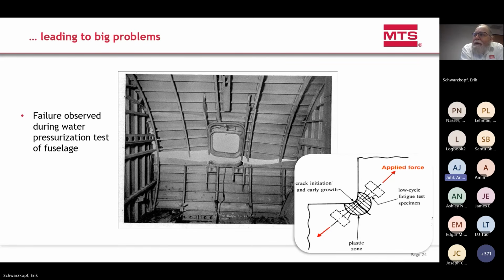The British engineers who made the de Havilland Comet needed to figure out what was going on. They took one of the airplanes, put it on the tarmac, filled it up with water, and pressurized and depressurized the fuselage, and they got a failure—an explosive decompression failure. It started at one of the corners of one of the openings. Essentially, that corner was going through a plastic strain change, plastically deforming, and that plastically deforming section of the material initiated cracks, and those cracks grew catastrophically.